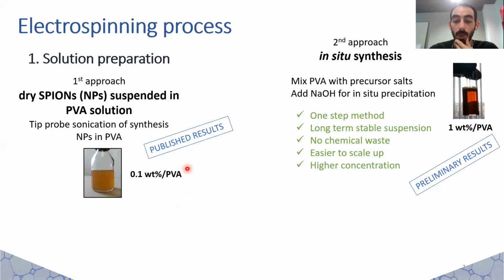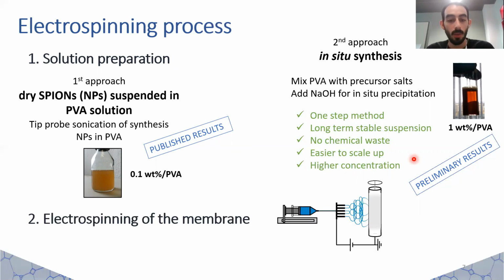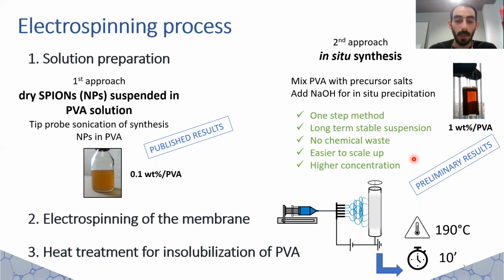In a second approach, precursor salts are dissolved in the PVA matrix solution, and then sodium hydroxide is added to precipitate the nanoparticles. This is a one-step method that produces a long-term stable suspension. There is no chemical waste. It's easier to scale up, and it allows a higher concentration in the solution. We have preliminary results for this, using 1% with respect to PVA. Then we electrospin the solution and perform a heat treatment of the membranes at 190 degrees Celsius for 10 minutes to insolubilize the membrane.